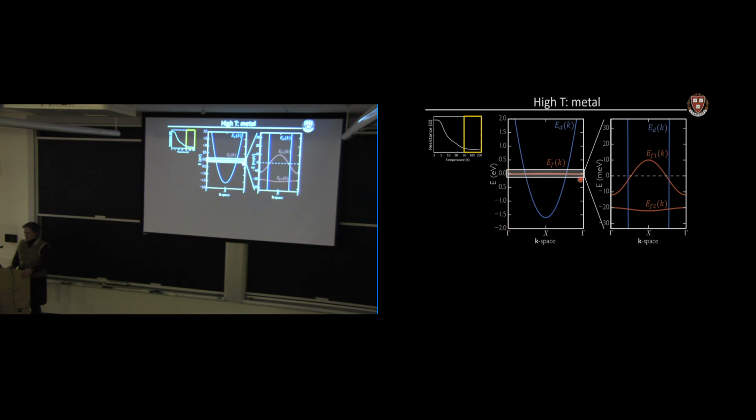But I'm going to zoom in on the Fermi level, and I see that these F states, there's actually a couple of F states that are closely spaced. I'm zoomed in about a factor of 100 here. So there's the Fermi level again. The conduction band has now become so stretched out that all you see is the 2 vertical lines here. And the F states are crossing it. So I'm still at high T. The conduction band is not bothered by the F states. But if I lower the T,